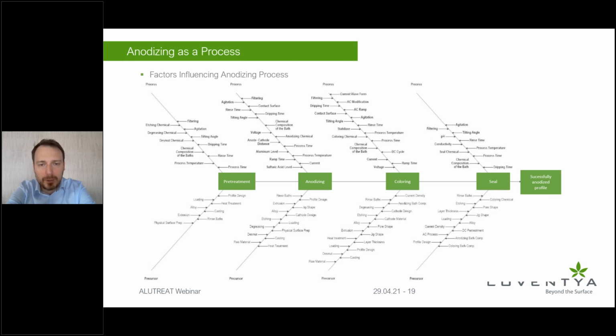This is very important to note, because as you can see here, all these processes prior or after the anodizing also have parameters influencing their performance. And because these processes are precursors of one another, it's not like each one of them has 10 parameters you should control, and you have at the end of the day 50 parameters. Because they work in combination, it's like 10 to the power of 10 parameters that you have to control. So going back, when I say it's a fairly easy process, it's more accurate to say there are about 1 million things that could go wrong with this process, especially in industrial application.